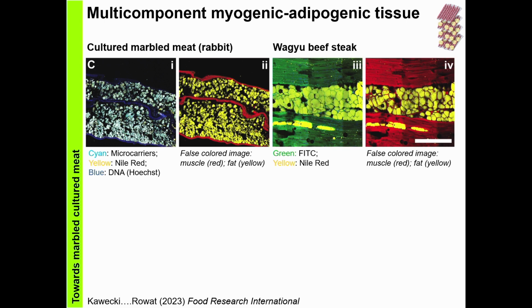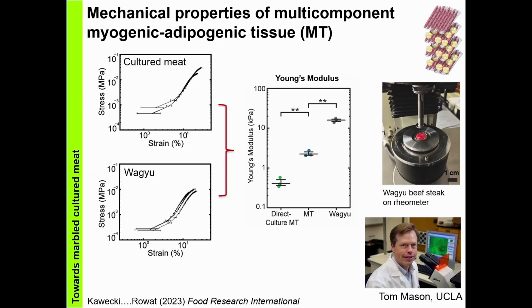But I think the exciting part here was that these tissues are forming from the spontaneous adhesion, and they're forming these cohesive structures by self-assembly. So we also did some mechanical analysis to understand, they look like the microtissues are adhered to each other, but are they really sticking together? So we used rheometry in collaboration with Tom Mason to quantify the stress-strain response of both our cultured meat samples, also compared to the conventional Wagyu.